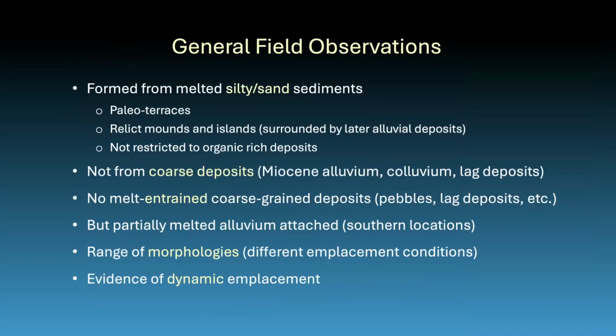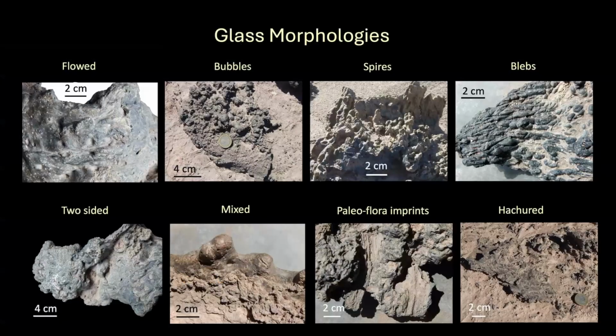So let's see. I'm going to skip over some of this. This is the very visual evidence. I already mentioned we know there are high temperatures associated with it because of the decomposition reaction. There's also evidence that the temperatures are very heterogeneous and very rapid. There are zircons that are perfectly fine crystals of zircon right next to decomposed zircon, which means there are very steep temperature gradients. And you cannot sustain a steep temperature gradient in a fire or any slow process. It's got to be a very rapid process. This is the only mechanism we can think of, one, to get those temperatures, and two, to get those kinds of gradients. And they're also very rapidly quenched. You can't quench rapidly without a steep temperature gradient, and that also implies that it's very transient.